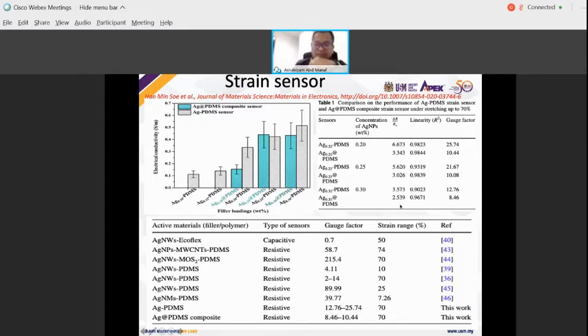For the strain sensor evaluation, we use the concept of resistance. When stress is applied, the length changes, and that causes a change of the resistance. From that evaluation, we evaluate the strain sensors in terms of gauge factor and the maximum stretchability. How do we consider the maximum stretchability? It is after 70%: if we return back to the initial state, the hysteresis can still be under control.